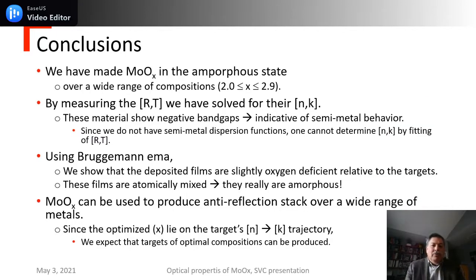In conclusion, we have made molybdenum oxides in an amorphous state over a wide range of composition. By measuring the reflection and the transmission, we have directly solved for their N and K, and that means we did not have to use any a priori dispersion function. These materials have negative band gaps, indicating that they have semimetal behavior. Because of the semimetal behavior, this is one reason why it will be difficult to fit these, because there's no known dispersion function, at least I don't know any, that has semimetal behavior.